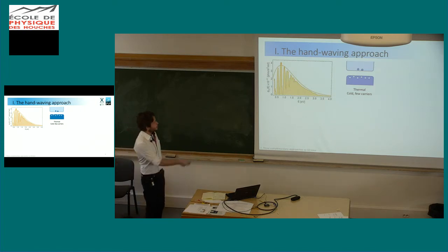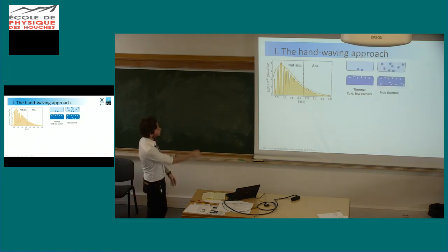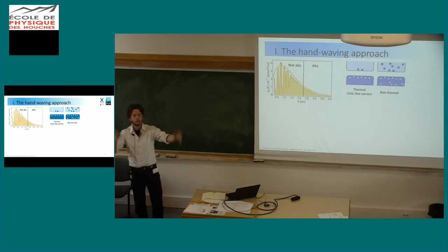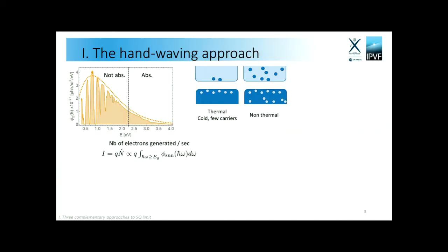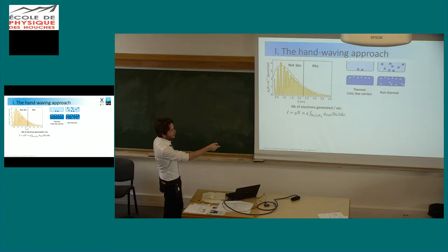Well, essentially, you start with a material where you have few excited carriers and they're cold. Then you shoot light into this, you absorb photons which have more energy than the band gap. You create a very messy state here, which is non-thermal. You can't describe this state easily. You've got carriers all over the place. But then due to interaction, these carriers will relax.